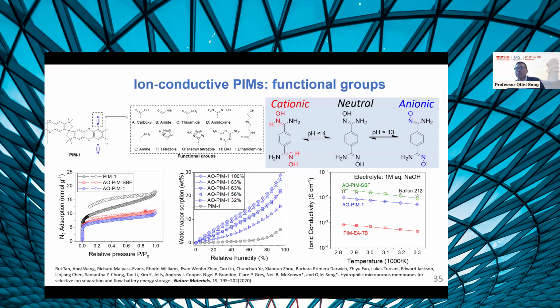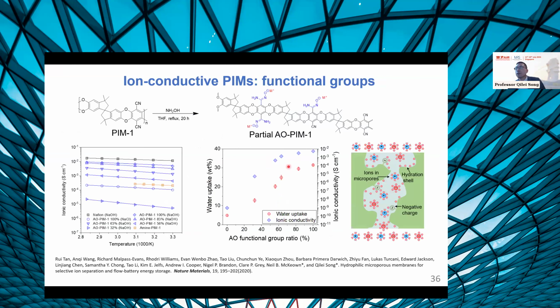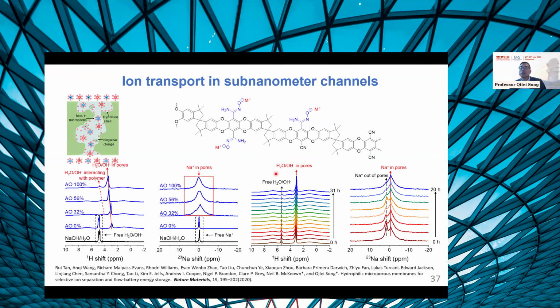So we were able to establish the relationship between the surface area, the porosity, and the water uptake. You can see that these materials absorb water molecules and form water channels, and they give decent ion conductivity. For some of them, AO-PIMs in sodium hydroxide give comparable ion conductivity to Nafion. We did a detailed study to look at the functional group and also the ion transport mechanism. We also collaborated with Professor Clare Grey at Cambridge to use solid state NMR to study the interaction between the water molecules and the transport of sodium in the membrane.